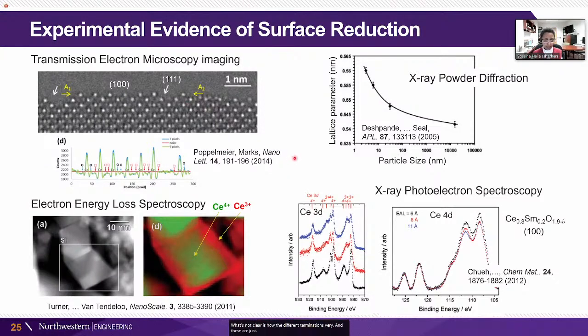And these are just examples in the literature showing that indeed, for example, there's more cerium 3+ on the surface than there is 4+ on that surface compared to the bulk. If you make the particles small, the lattice parameter increases, and that's attributed to having more and more cerium 3+ because you have more surface area. So a lot of body of evidence that says the surface is more reduced, but again, not really a comparison of different terminations and understanding what that means for the catalysis.